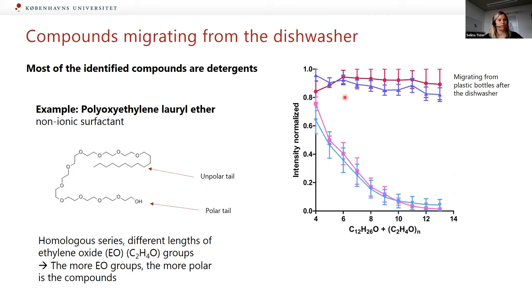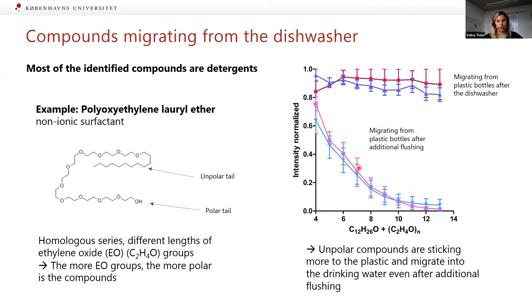When we were looking at what was leaching out of the bottles into the drinking water right after the dishwasher process, we see here on the x-axis different lengths of these ethylene oxide groups, and they are all leaching out in similar high amounts. But after we carefully flushed this bottle and filled it up with drinking water again, we see that the more polar compounds are removed, but the less polar compounds, so the shorter the polar tail was, the more was still in the bottle. So the unpolar compounds stick more to the plastic and migrate into the drinking water even after additional flushing.